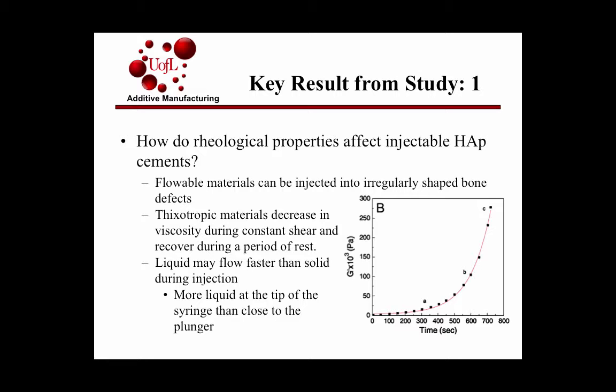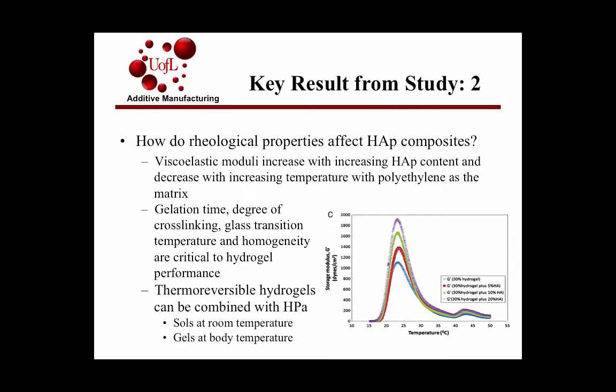The issue they discovered with this in the research was that when people design these, they don't necessarily consider that when you put this material in a syringe, the liquid will flow faster than the solid. So as you're injecting it, with the lower pressure at the needle, all the liquid will collect there, and that will inject first. And then left closer to the plunger will be just like a wet powder, basically. So you get to the end, and maybe that powder won't flow through the needle, and you've not accomplished what you want it to. So they just addressed that as a potential issue for the development of these materials.